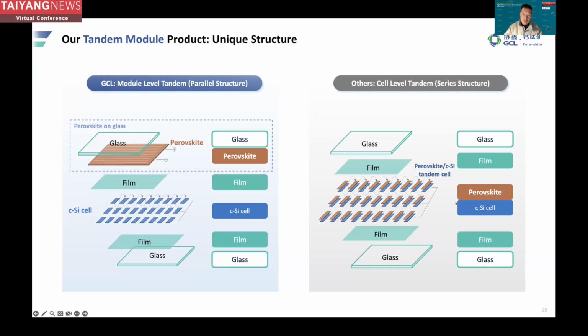And the problem with this design is that although they can make a pretty high power conversion efficiency with a very small area, like 1 square centimeter, they can reach 33.9%. But when they come to a larger size of the cell, like 200 square centimeters or a little bit more, the efficiency quickly dropped to something between 25 to 28. And, well, I would say it's not that significant an improvement compared with single junction silicon cells. But with the module scale, now we are able to achieve 26.3. Now it's already better than any kind of silicon module.